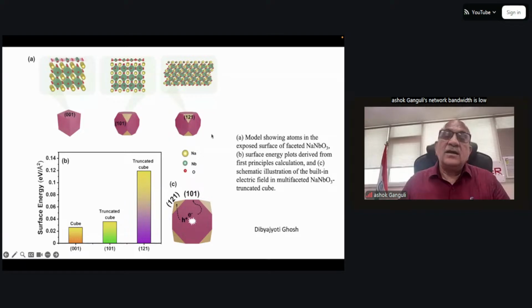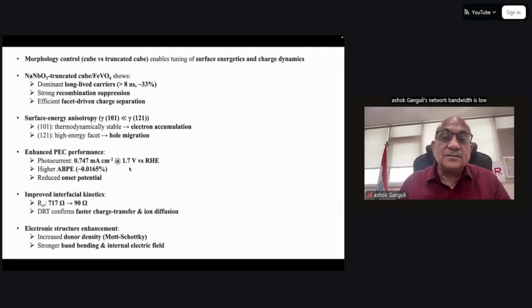And based on that, you can tell what would be more stable. Electron would be more stable there or less stable there. And that helps you in explaining the data which we have discussed in the previous slide. So you can calculate surface energy anisotropy, which makes the electron accumulation or hole migration, and ultimately it leads to increased donor density, stronger band bending, and stronger internal field. So this is whatever I was telling you in terms of facet control for increasing the efficiency.